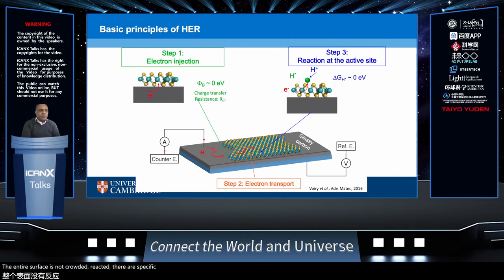There are specific thermodynamic sites where the HER reaction occurs. And the third step is that when the electron reaches the active site, it has to combine with the proton, so you have adsorbed hydrogen. And when you have a sufficient number of hydrogens adsorbed on the surface, there's a driving force for them to evolve as H2 gas. And so the adsorption and the desorption energy for an ideal HER catalyst should be thermoneutral. That is, the delta G should be essentially zero.